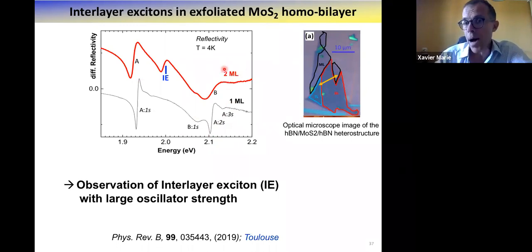When you do this on the exfoliated homo bilayer, you do observe the A exciton, again the B exciton, but you clearly see between the A and the B a rather strong transition. I recall this is a reflectivity, so it corresponds more or less to absorption, which we assign to interlayer exciton, as I will show now. And the surprising point is that it has a rather strong oscillator strength when you compare it in this very simple experiment to the intralayer exciton oscillator strength of the A or B exciton.